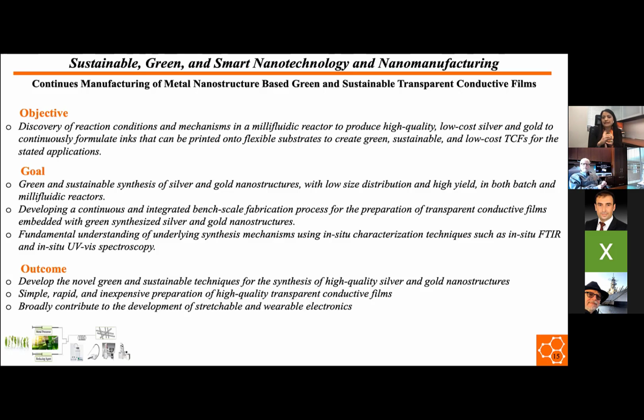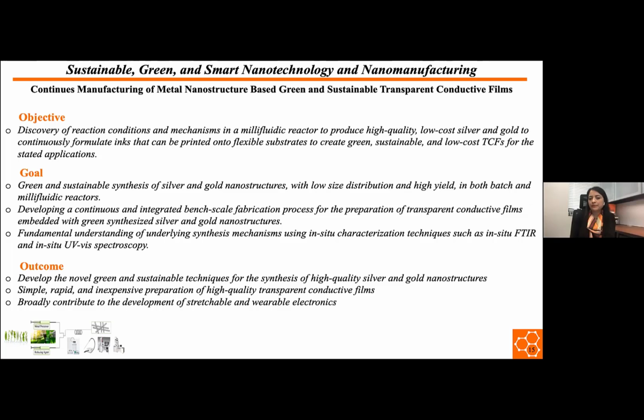Then we can connect this system to the printing machine to create transparent conductive films on the surface of paper or plastic. Also, we are really interested to understand what's going on behind this process using different characterization techniques available in our lab. For example, if there is a specific green reducing agent that can act both as reducing agent and capping agent for the synthesis of a specific metal nanostructure, what are the functional groups that are responsible, or what's the reaction mechanism behind this process? Because by having this understanding, we will be able to control the process better. And definitely the outcome will be novel, green, and sustainable techniques for the continuous synthesis of silver and gold nanostructures, and it will broadly contribute to the development of stretchable and wearable nanoelectronics.